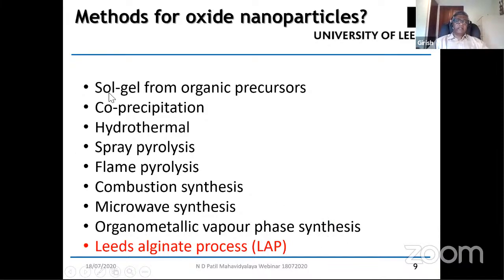So with these drawbacks and different kinds of limitations of various techniques, we looked at different techniques and we stumbled upon this particular technique, which we named the Leeds alginate process. This is a very simple process. It's an ion exchange process. You have the polymer, which is alginic acid or sodium alginate, which is basically a polysaccharide. It has carboxylic acid groups in it, and those carboxylic acid groups are very active and can be easily ion exchanged with various metal ions from the aqueous solution. So these are aqueous precursors, unlike the organic or organometallic precursors used in these two methods.